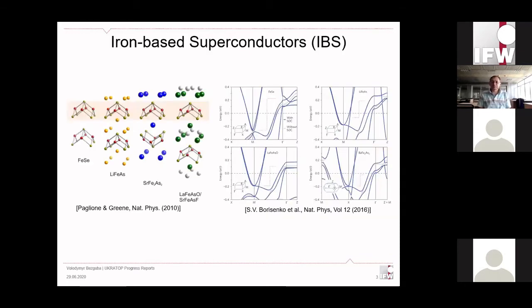So, iron-based superconductors were first discovered in 2008, and as you probably know, they are high-temperature superconductors with transition temperature Tc going as high as 55 Kelvin. Unfortunately, the nature of high-temperature superconductivity still remains unknown, and while these compounds might have different crystal structures, they all share similar building blocks, which are iron-selenium layers or iron-arsenic layers.